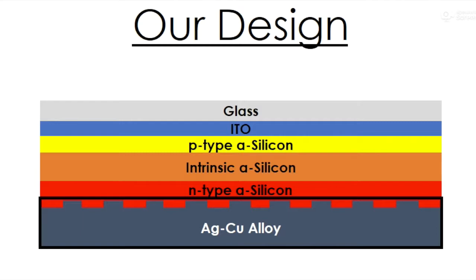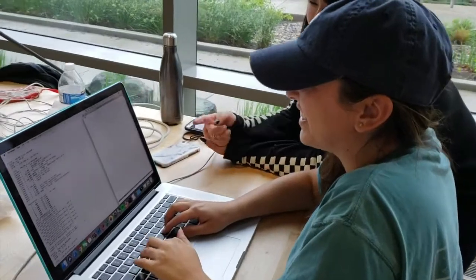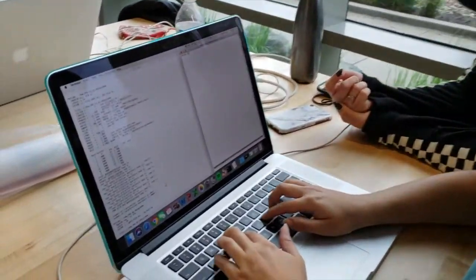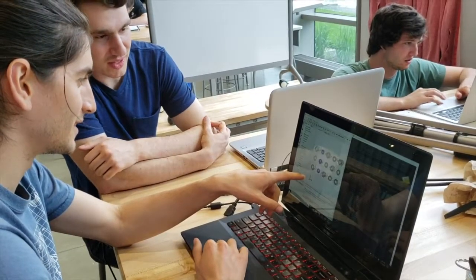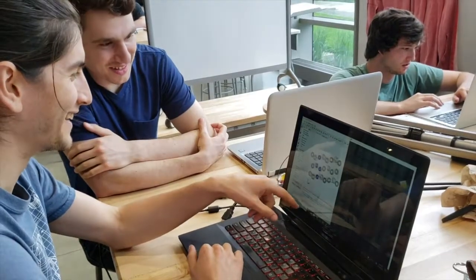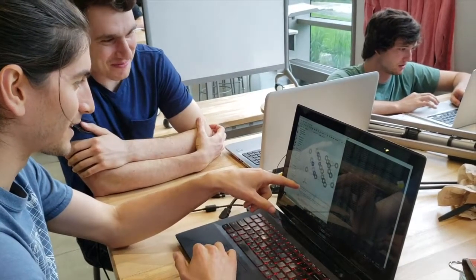To model the performance of our device, we used two separate techniques. Our first step was to predict how the dielectric function changes with alloying. We did this by simulating alloys ranging from pure silver to 50% copper and calculating their dielectric function using first principle methods. Each simulation ran on UMD's Deep Thought 2 supercomputer, and returned the full dielectric function as a function of energy, which we used to observe how increasing copper content changed both the resonance frequency and the lossiness.